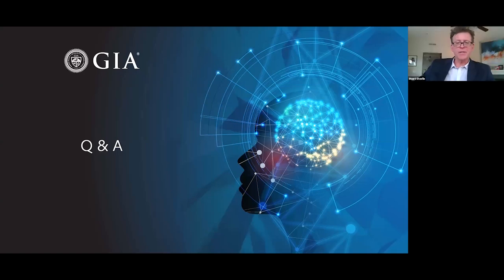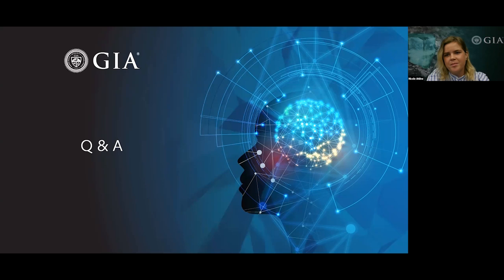All right, and let's have some inclusion talk here. Can you tell us how you get rutile as both silk and crystals inside corundum? So when you're looking at rutile and corundum, they can be protogenetic, meaning they formed prior to the corundum; syngenetic, they formed with the corundum; and epigenetic, so they formed after that corundum was grown. That elongated rutile crystal that we saw in that Afghanistan corundum is probably syngenetic.